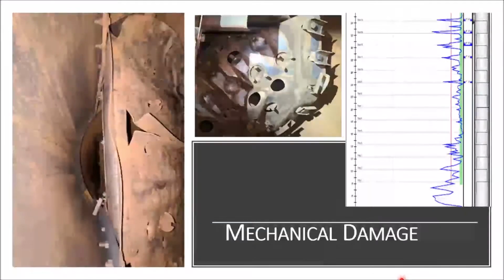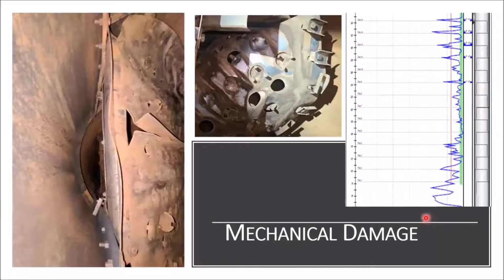So, a couple of pictures. This was a plant that was supposed to make less than 100 ppm of H2S. It happens to be a refinery, but I can show you the pictures. They were actually processing at rates above 1,000 ppm on the outlet of the contactor. So obviously something was wrong. We went through all the amine parameters. They were circulating the right amount. It was well regenerated. The temperature was good, and it's still not working.